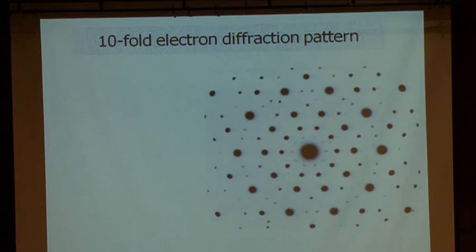However, based on my previous knowledge, I thought that what we have here is a series of defects in a crystal called twins. Twins are like grain boundaries, but in a very special angle between them. So if these, in my fingers, designate atomic planes, then we have another one which is mirror image with this atomic plane. And this is a twin of that. And in between them, we have a twin boundary. If you have 5 of them together, and you take a diffraction from all of them, or 10 of them together, then you will get a diffraction pattern, which is a composite diffraction pattern, not from a single crystal, but each spot comes from a different one, and they can do that. It can look like that.